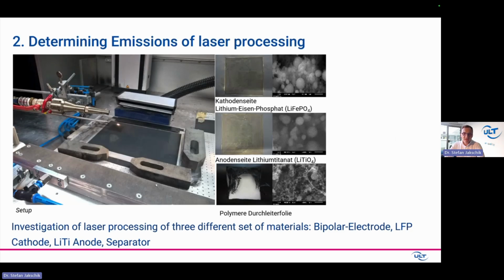I want to walk you a little deeper into the particles which can be exposed during laser processing, and this is a test we made in one of our labs. You have a laser production on an electrode surface, and we investigated lithium titanate and LFP, which is nowadays the common electrode, and you see the kind of particles we see there. A lot of balls, dendrite kind of particles. Most of them have a size of 100 nanometers or below. So barely visible, by eyes definitely not, and also by many sensors and vision techniques you would not recognize them. So a very good capturing of the particles is extremely important on that side.